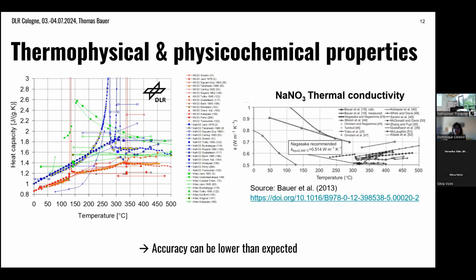Then some warning about thermophysical properties here. We see here a diagram of heat capacity values of pure salt, potassium nitrate, sodium nitrate, and here also of the mixture. And you see that there's quite a lot of scattering of data, so you need to be very careful about the quality of thermophysical property values. Also, here's an example of thermal conductivity. You can find everything from 0.5 to 0.7, and then people expect 3 digits of accuracy, but that's not the case. But can you claim which ones are the accurate ones, which are the good ones?